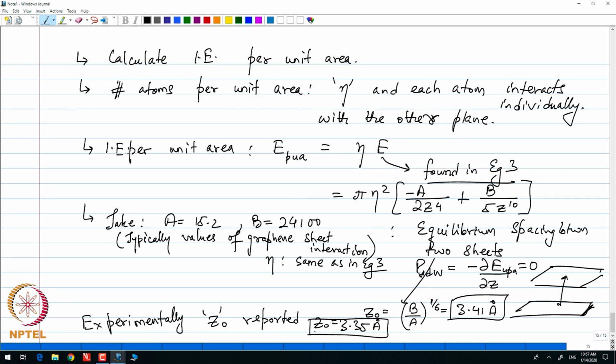So, the question that is asked is, where is the discrepancy in our model? The discrepancy lies in the structure of graphene itself. We know that graphene has parallel sheets which are almost equidistant apart. Which means that any point on one sheet of the graphene not only interacts with its nearest graphene sheet, but also interacts with all the other graphene sheets which are at distance z, 2z, 3z, 4z and so forth. So, we must include all those other graphene sheets which are at a larger and larger distance away from the sheet under consideration. Okay. So, this is the issue that I want to highlight.